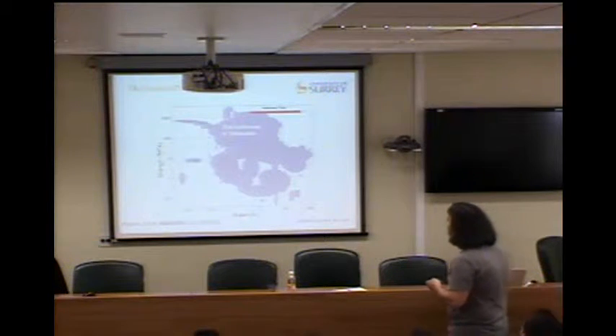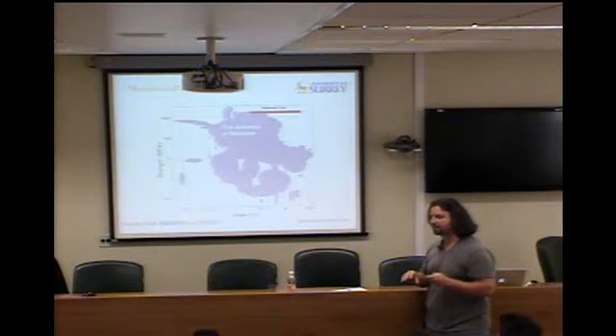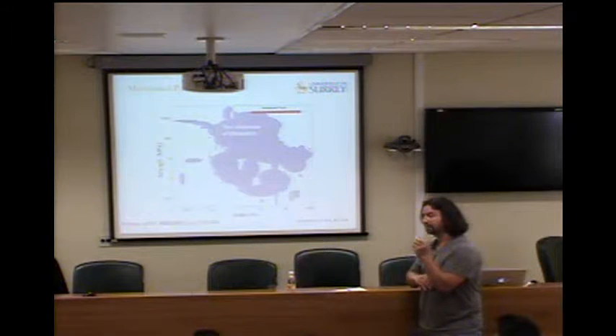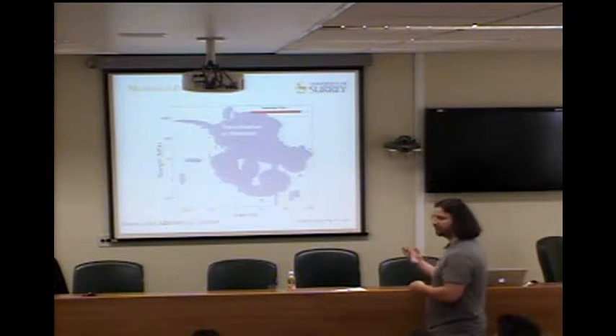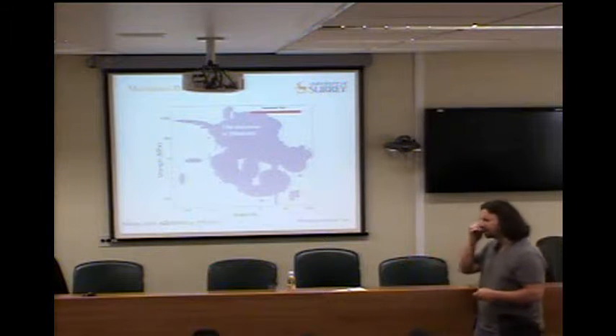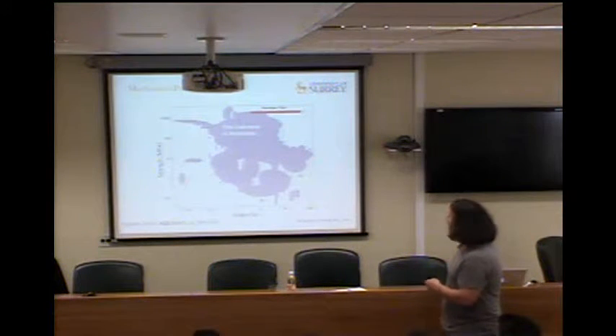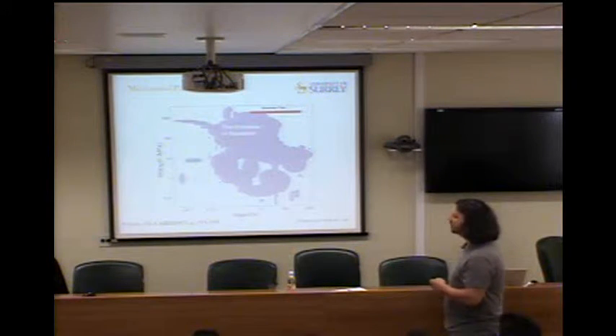And if we look at the mechanical properties, so this is if we plot strength versus strain. So I said to you that for a tough material, you have large strength and large strain at break, right? So you're somewhere up here for toughness. So to give you an idea, this is a universe of materials. So up here we have ceramics. Ceramics are very brittle, so they don't have much strain before they break, but the strength is very large. Like so-called superfiber materials like Kevlar is up here, okay? But our nanotube fibers, depending on the morphology, have very impressive properties. So it has very large toughness, but it also has strength at break, which is close to 3 gigapascals, okay?